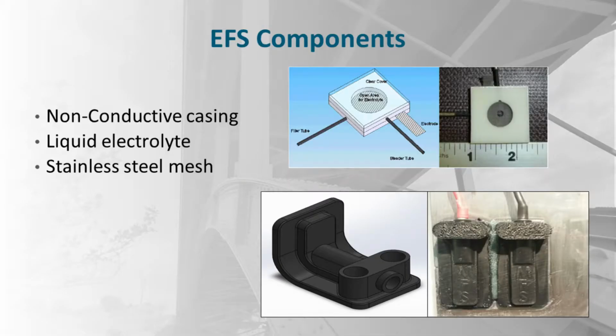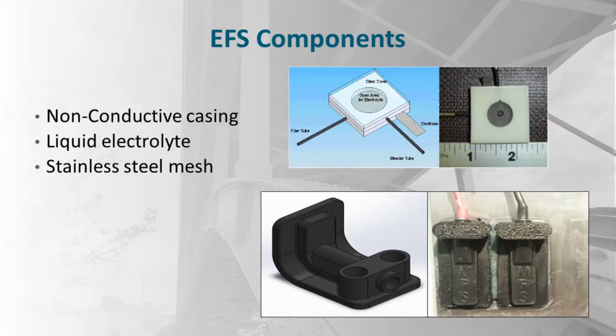In the 2 pictures on the bottom is the long-term sensor. These sensors can actually be made out of any shape to fit anywhere in the bridge. They're usually custom made, so they are not necessarily flat. In the picture on the bottom right, you will see 2 of them, a pair of sensors. The one on the left, the one that has the red wire, is installed on top of the crack, or nearby where the crack should propagate to. And the one on the right is the reference sensor. We need 2 sensors in order to know if there's actually crack activity.